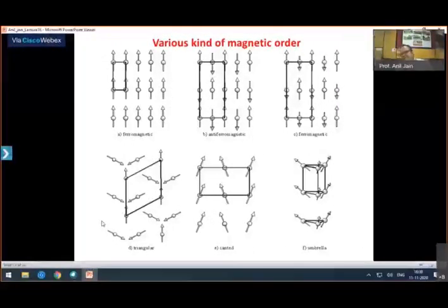If you have seen this neutron scattering, as I told you, your average scattering length gives you the information about the coherent scattering, and deviation from the average, which is like the distribution of your spin states and isotopes. Any deviation of the scattering length from the average gives you the background, which is incoherent and present everywhere. You can have structural defects in the material. This can also contribute to the background.